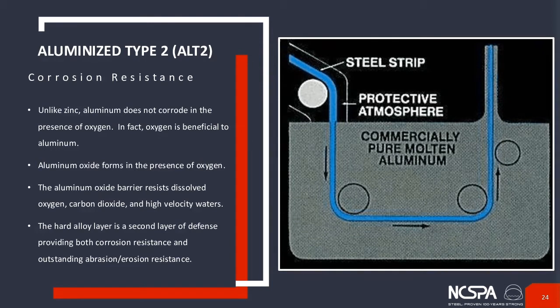aluminum coating, and you can see that in real life if you've ever seen a brand new aluminum, let's take a bass boat or something like that, and it's nice and shiny when you take it away from Bass Pro and stick it in the water, and you come back a year later and it's all kind of gray and waxy. That is the aluminum oxide that forms on the top of the aluminum, and it actually provides a very tenacious coating on the top of the aluminum, and that's part of the system that allows it to resist corrosion due to presence of oxygen, carbon dioxide, water, things like that, aggressive environmental conditions. So it's very unique and very different than galvanizing.